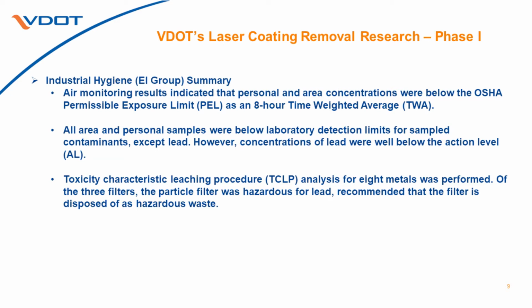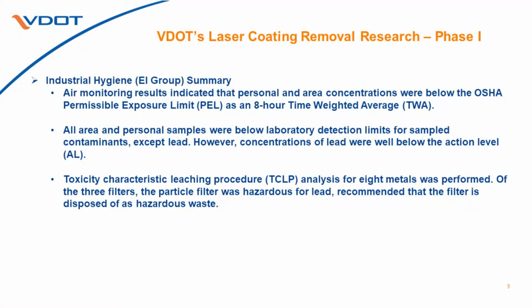The air monitoring results indicated that personal and area concentrations were below the OSHA permissible exposure limit, that all area and personal samples were below laboratory detection limits, and that the TCLP analysis for 8 metals was performed, and of the 3 filters, the particle filter was hazardous for lead. So again, from a worker protection point of view, we have determined, and I'll go into this in a little more detail, that individuals can use this laser to remove lead coatings and not require any of the OSHA personal protective equipment or anything like that.